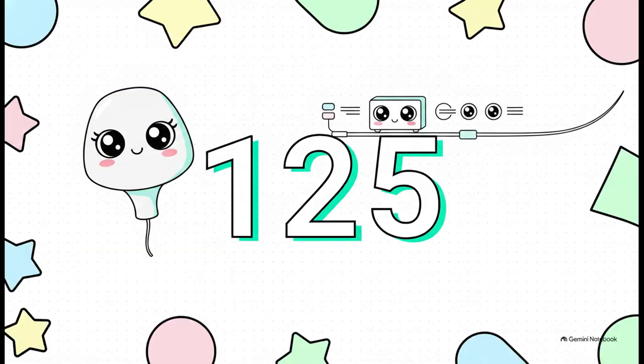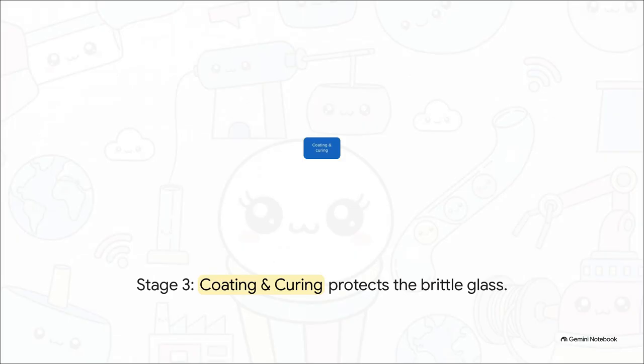Now contrast that blinding heat with extreme microscopic precision. As the glass is pulled, that baseball bat-sized preform is stretched down into a fiber that is exactly 125 microns thick. A laser micrometer is actually measuring this diameter thousands of times per second, adjusting the draw speed instantly to keep the thickness perfectly accurate to within a fraction of a micron. And incredibly, as it stretches, the internal proportions of the core and the cladding stay exactly the same. No way, right? Moving right along to stage 3, coating and curing.